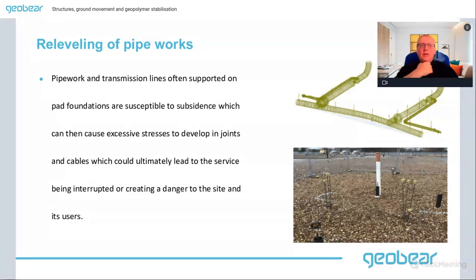structures. There's a case I've recently been involved in Sweden where we were lifting some fairly large pad foundations to a warehouse, and the total weight lifted was about 55 tons on a large pad foundation. And that was lifted about an inch, so 25 millimeters. So we can lift relatively heavy loads. So lifting pipe work that's nowhere near 55 tons, or was that 550 kilonewtons in those units. So really quite heavy loads can be lifted.